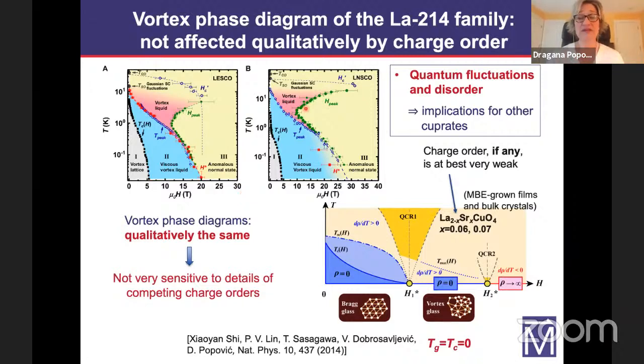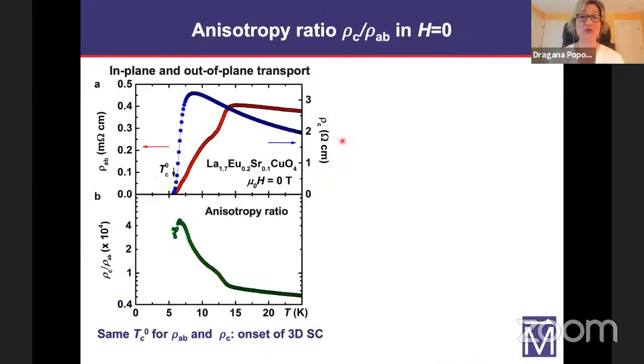So now that we have established these phase diagrams, what we actually want to do is address our main question. And this is, we want to look for evidence of pair density waves. So we want to focus on the study of the anisotropy ratio, which is the ratio of the out-of-plane to the in-plane resistivity. So here are results again on LESCO in zero magnetic field. On top, we see that the in-plane resistivity shown by this red curve has this drop.